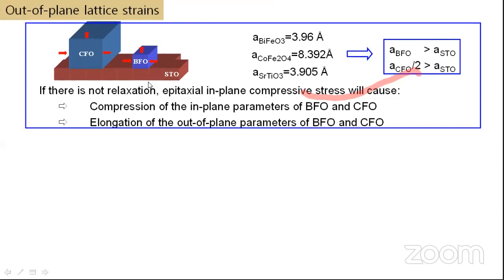So how does this lattice strain work? The lattice parameter of bismuth ferrite is 3.96, and the lattice parameter of the strontium titanate substrate is 3.905. So bismuth ferrite has a larger lattice parameter than the substrate. What will happen is there will be an in-plane compression, and to maintain the volume there will be an out-of-plane expansion. If you grow bismuth ferrite alone on a strontium titanate substrate, this is what will happen: in-plane compression and out-of-plane expansion.